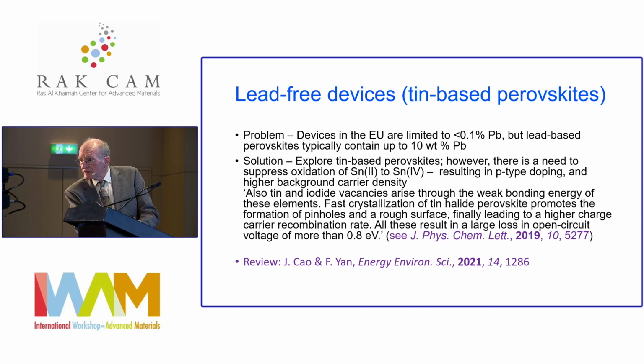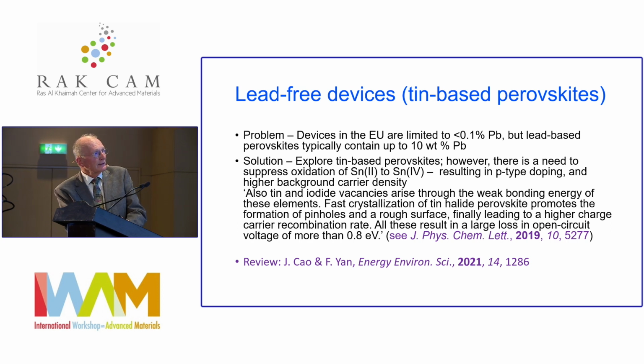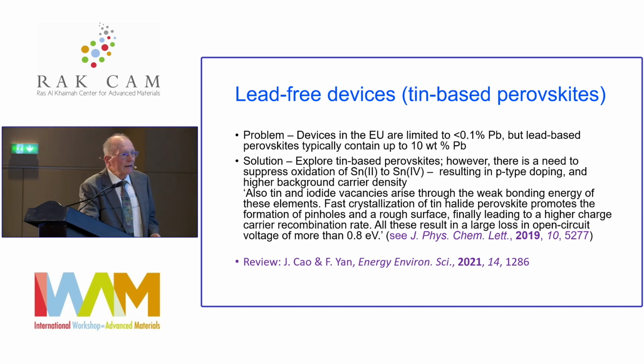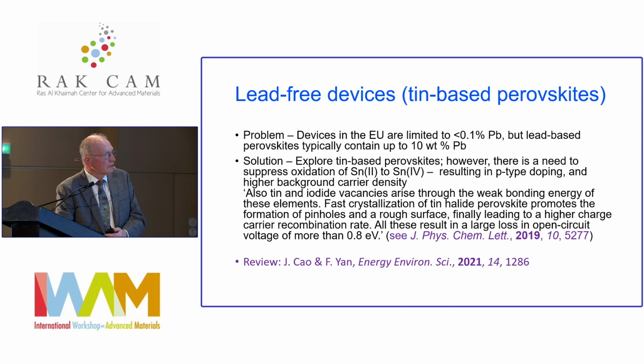The problem with tin, though, is it's even more easily oxidized to tin 4, and that produces p-type doping and higher background carrier density. And then there are vacancies that arise through the weak bonding energy of these elements, and fast crystallization promotes pinholes and a rough surface and a higher charge carrier recombination rate. All these result in a large loss in open circuit voltage of more than 0.8 electron volts. That's a lot to give away through morphology.